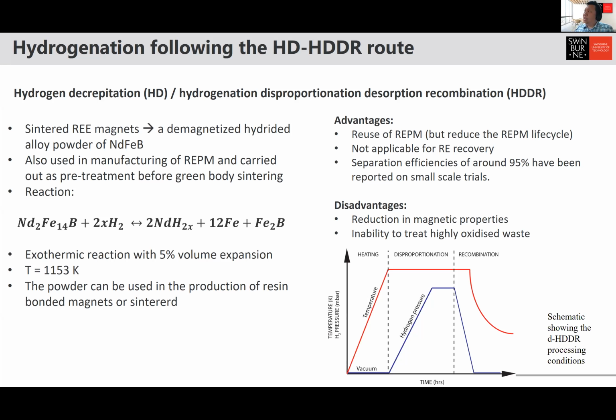But the second REPM, the recycled REPM, usually has a lower life cycle. The life is shorter. Of course, in here, we cannot use it to recover the rare earth. We just reuse it to make REPM, right? It has been reported that the efficiency of the separation can be about 95%, right? Which is pretty good. One of the disadvantages is there's a reduction in the magnetic properties, so it's not really as good as the original, for example. And the same thing in here, you cannot really use REPM that is heavily oxidized.